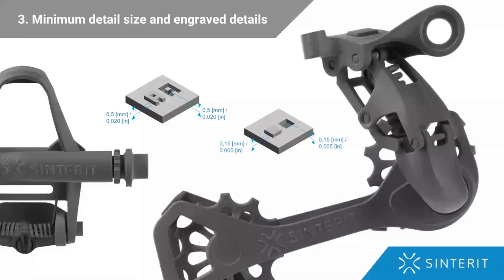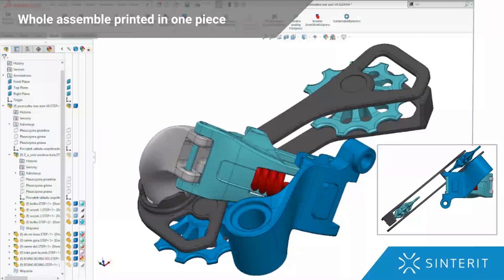A good way to ensure there are clearances is creating offsets of about 0.15 millimeters to 0.2 millimeter in height. So using SLS 3D printing, you can print moving parts in one go and have your entire print ready for much faster printing because of it.